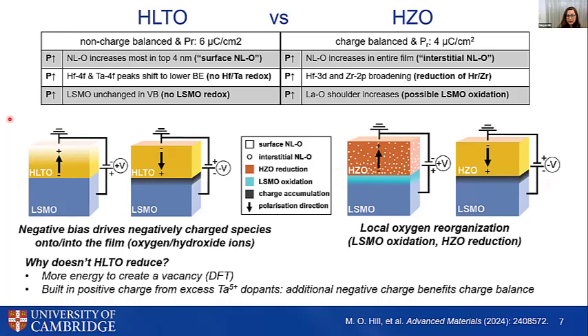And the differences that we see here, why we get this reduction in oxidation of HZO and not in HLTO, could be for a number of reasons. One of them being that, according to DFT, it takes more energy to create an oxygen vacancy in HLTO compared to HZO. But also, we know that we have an excess positive charge from the excess tantalum dopants in the HLTO, which might benefit from drawing species from the atmosphere into our sample for charge balance effects.